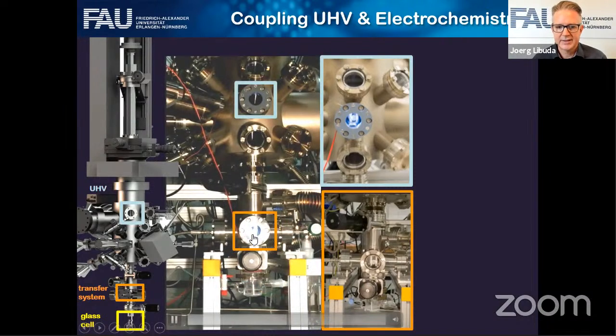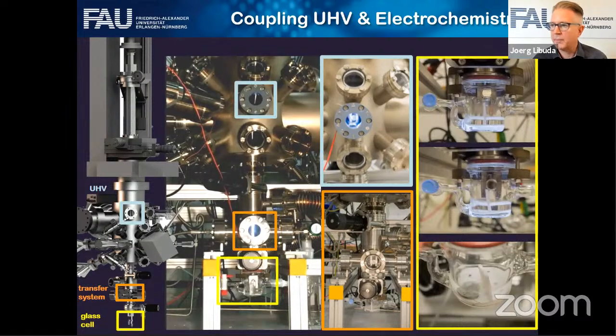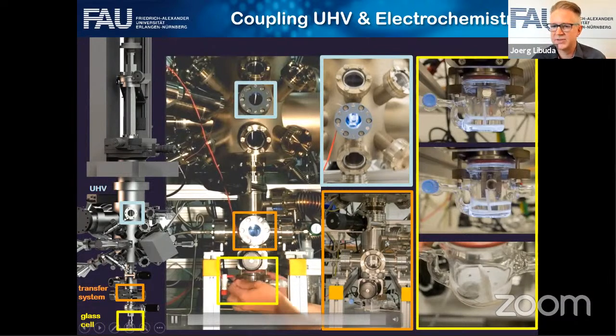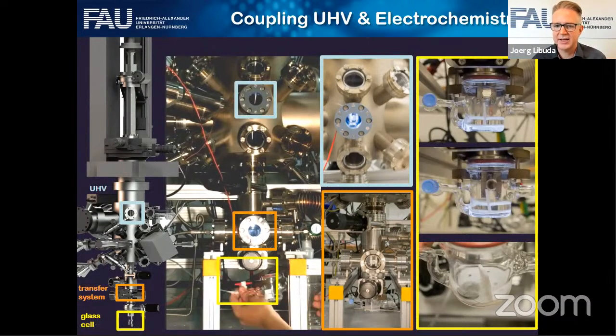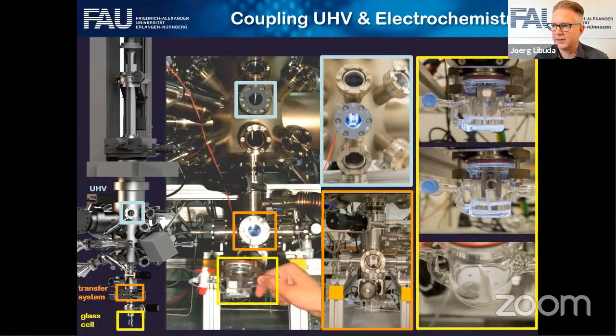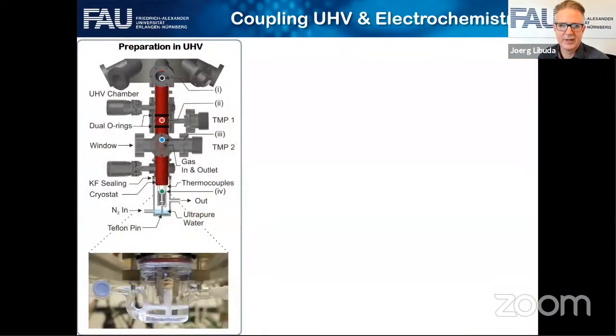And then the sample is moving down here into this vessel where you have ultra-pure water, and that is purged with the ultra-pure gas. And then the single crystal is disconnected from the sample holder. It will drop into the water. It's protected by the water and the atmosphere. You can take it out and do electrochemical experiments with it. And that's our way of connecting these two worlds.